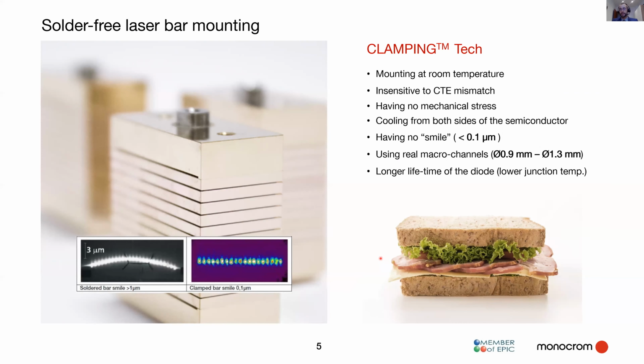Another effect is that due to the avoiding of solder paste and solder materials, we are insensitive to a coefficient of thermal expansion mismatch, meaning that there is no strict connection between the laser bar and the electrode. So the electrode can still release stress if it's heated up or cooled down due to current or environmental temperature changes. This has an advantage because we also can cool from both sides due to the sandwich structure. Both electrodes are made of copper, and so we can ensure that we have good thermal contacts and can extract the heat quite efficiently.